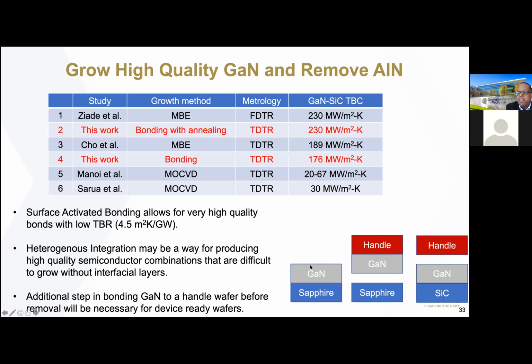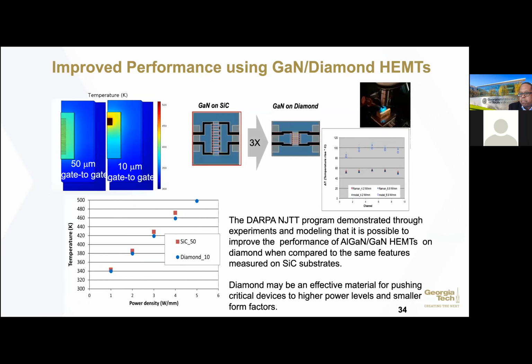One of the things I will have to admit though is that what we have shown you here is GaN bonded to silicon carbide. Typically, if you're going to produce this, because of the polar nature of GaN, when it's grown on sapphire, you want to have this surface up. So typically what you'd have to do is go back, bond this to a handle wafer, and then take this and bond it to the silicon carbide and take the handle wafer off. We did not do that in our research experiments, but it's an extra step that can be done in industry. It's currently being done with GaN on diamond, and I'll show you some of that in the next set of slides.